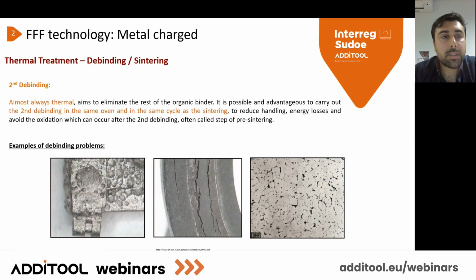And then we have the second debinding, and the second debinding for every process is almost always thermal. And the objective is to eliminate all the rest of the organic binder. So it is advantageous to have the second debinding in the same oven and in the same cycle as the sintering to reduce handling, energy losses, and avoid the oxidation. It can occur when we open the oven. Okay, so we advise to do it in the same oven.